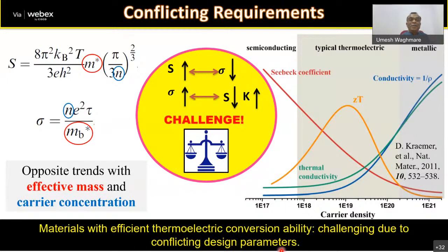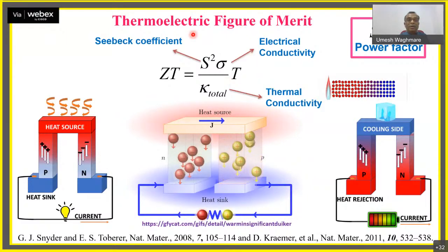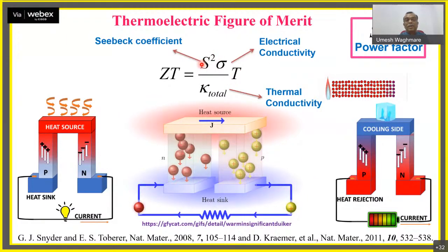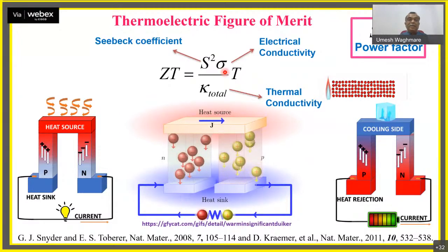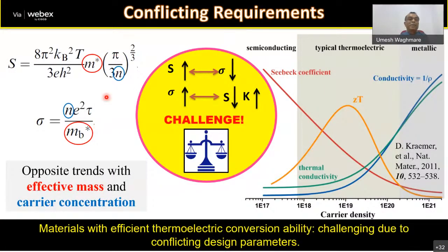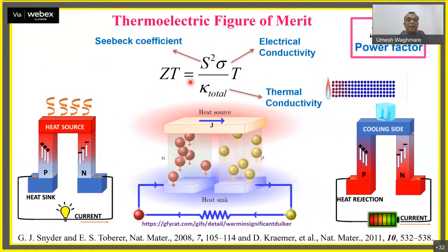So these conflicting requirements are shown here in a more quantitative sense. The Seebeck coefficient, as you will see, is directly proportional to the effective mass of electron carriers and inversely proportional to the density of these carriers. On the other hand, electrical conductivity is directly proportional to the carrier density and inversely proportional to the mass. So the numerator of this figure of merit, which is called the power factor, because this is voltage times current, involves conflicting optimization. If you optimize S, you minimize sigma, and vice versa. And not only that, if you increase sigma, the electrical conductivity, you also increase thermal conductivity, and that works against you as well.